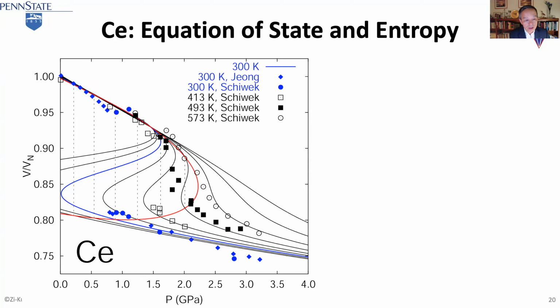You can separate phases. You separate the 2 phases here. For example, look at the dashed line. You see they separate. You have phase separation here because the energy will be lower by that process, the minimization of the homogeneous energy. So it's a very nice agreement with experiments. Remarkable. Again, there is no model and no fitting parameters.